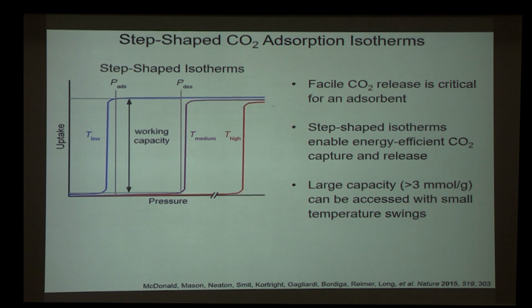I need to point out at this juncture that any adsorbent we use in such a process needs to be very good at capturing CO2, but it also can't be too hard to get CO2 out. Typically in the process, you would first capture CO2 and then use heat to drive the release of carbon dioxide, thus regenerating your adsorbent and making it ready for another cycle of capture. And this would need to be repeated many times. And if you need a lot of heat to drive the release of CO2, the adsorbent will be too energy intensive to implement in a practical process.